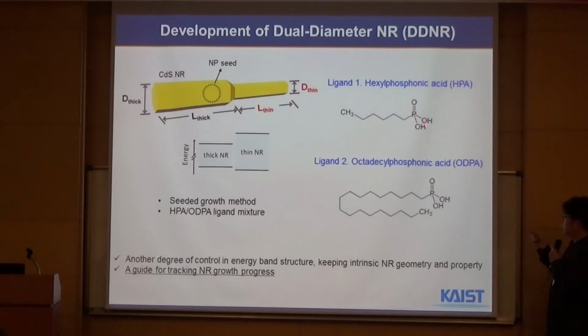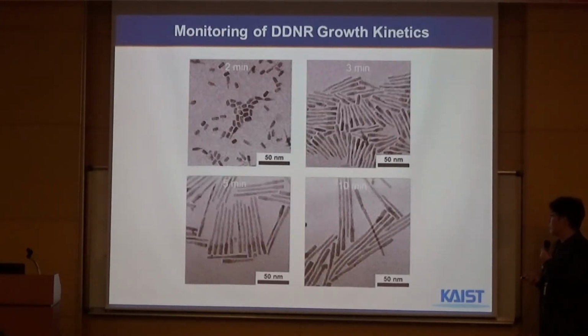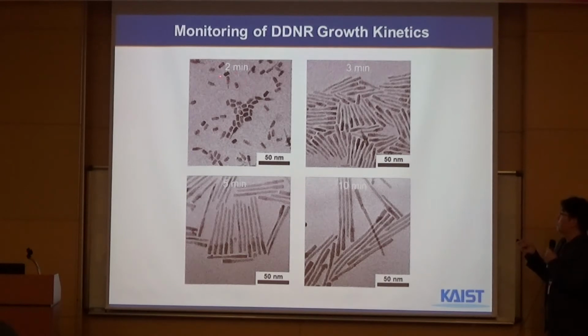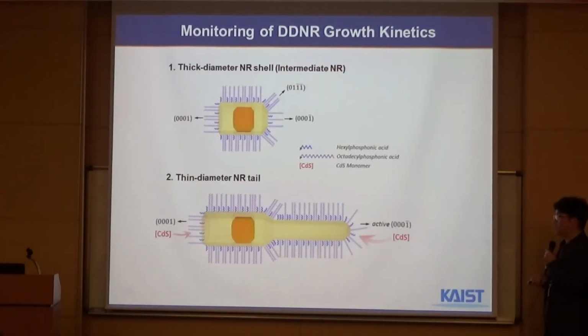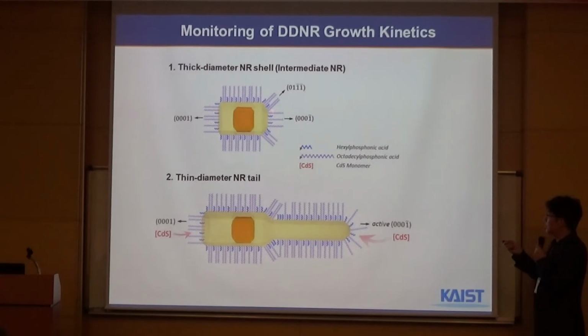We used two different ligands, shorter ligands and longer ligands, both are phosphonic acids, and then grow in colloidal batch. And then by monitoring the growth of nanorods, you can see that growth is going to be drastically different. You can see that there's a thick nanorod forming, and then later you have extrusion of this smaller nanorod component, and then you see the growth of smaller nanorods more drastically in longer time. Basically, because of the passivation of the surface layers using hexyl phosphonic acid and octadecyl phosphonic acid, and their interplay on the surface, we were able to get this thin diameter nanorod tail.